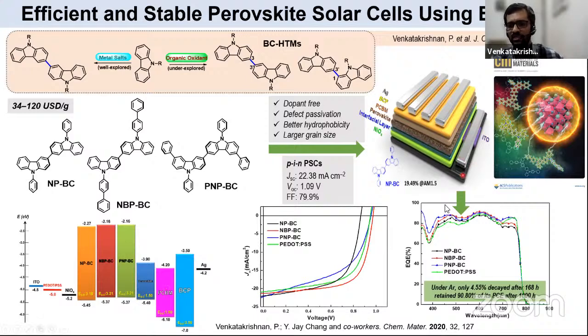Okay, so if you look at the stabilities, we've also done the stability studies for these compounds. When this was put into the perovskite solar cells under argon atmosphere, only 4.55% decayed after 168 hours, but retaining 90.8% of its power conversion efficiency after 1000 hours. So this gave us some hope that indeed we could synthesize nice hole transporting materials based on the strategy that was explained earlier, fulfilling all the ideal characteristics of a hole transporting material.